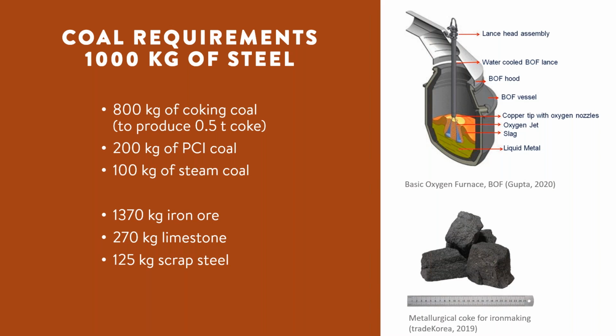The final stage of crude steel production converts the pig iron, which has 4% carbon content, into a crude steel, which will have ultimately a carbon content of less than 1.5%, sometimes a fraction of a percent of carbon, depending on what's required. Pure oxygen is injected at supersonic velocities into the molten mix of iron and scrap steel. The scrap acts as a temperature moderator as well inside the basic oxygen furnace, which you see up in the top right here. The oxygen oxidizes most of the remaining carbon to form carbon monoxide and CO2, as well as oxidizing other contaminants to form slag for later removal.